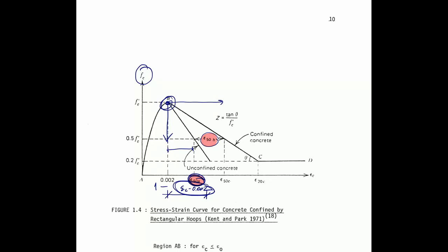And basically, even though it is not confined, the shape that you see after the failure, okay, is supposed to be like this. So this is the maximum tensile strain plane. That means once this cracks off, you do not have any tensile strain. The maximum is just gone already, so you don't have much more than that. So under this hourglass shape, you still can maintain further. Well, I'm not saying that it's going to go to infinity, but it will not get smaller, basically. It reached the equilibrium state already.